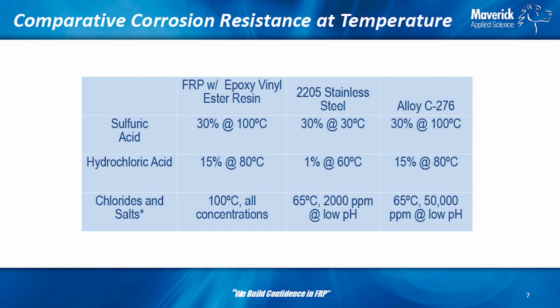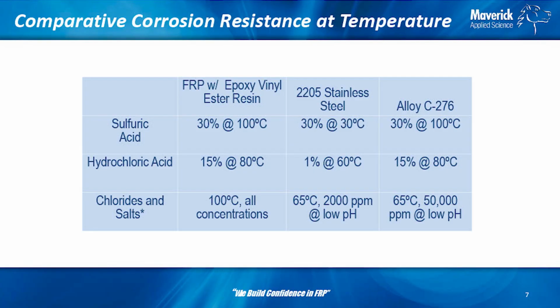So Kevin showed something a little bit similar to this, not exactly. If we look at just the epoxy vinyl ester resin, that's kind of what Kevin had talked about before, and then he had the Novolac epoxy. So for sulfuric acid, it works well for up to 30% concentration and up to 100 degrees C. So pretty high temperature. That's pretty much the high end of process temperatures that we see.